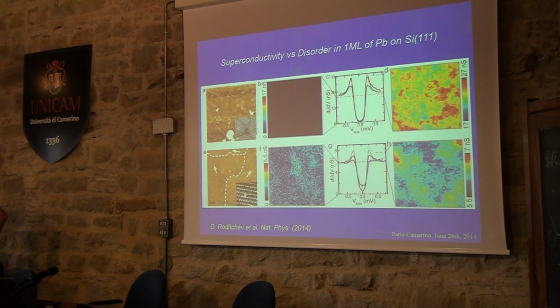The problem is as follows. If you have a very nicely ordered square root 7 by square root 3, you basically have the superconductivity quite homogeneous. And Professor Hasegawa will tell you about this. But however, if you have twin boundaries, as those that are reported as dashed line, or also some stacking fault lines, or also some individual atomic defects, then you get this rise of zero bias conductance.